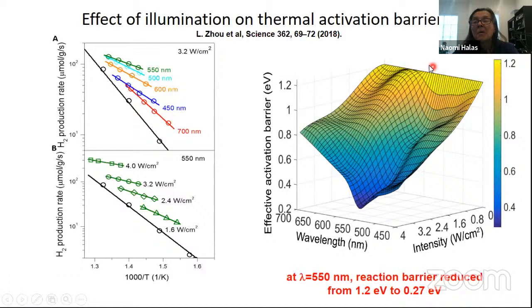So this axis here is the reaction in the dark. And then on one axis, I have intensity and on the other one I have wavelength. So just as I show you in the very top part of this plot over here, as I turn on the light, I lower the barrier. And especially at this wavelength here, this is the most effective wavelength, I lower the barrier a lot. I lower the barrier by almost a whole electron volt at this wavelength. And also I lower this as a function of intensity.